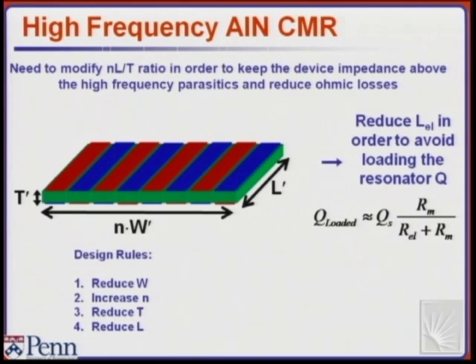peak. And it's actually very similar to what you see in surface acoustic wave devices which were developed 60 years ago, and they're based on basically interdigitated technology like this one. They're just not freed from the substrate, and they use surface waves instead of bulk waves. And that's an advantage of SAW over, for example, F-bar. Then when they change the shape or they scale it, they see other modes of vibration superimposing.